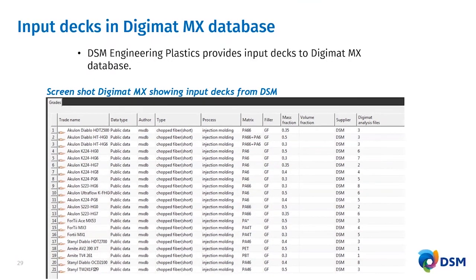Okay, so since DSM approaches all of our material sales as a partnership, we have measured the stress strain behavior of our materials to derive thorough input decks for the Digimat software. This enables us to work even more closely with our customers and to identify future needs for material models, such as the effects of temperature, humidity, and crash behavior. Our teams check the accuracy and robustness of our material models by using in-house testing on injection molded parts to validate that our material models provide accurate predictions. Through this rigorous testing, we have successfully verified excellent results for stiffness, eigenfrequencies, and load of failure. We've also developed new models to get good results for the fatigue performance of our materials.